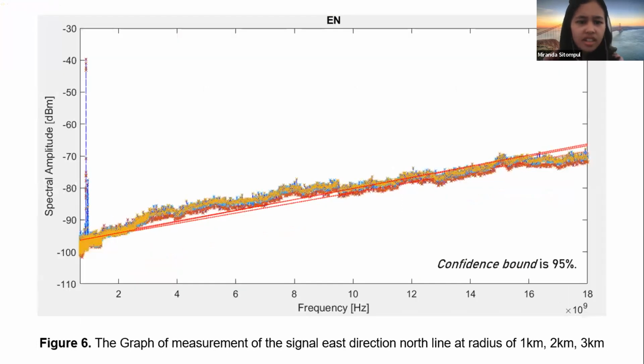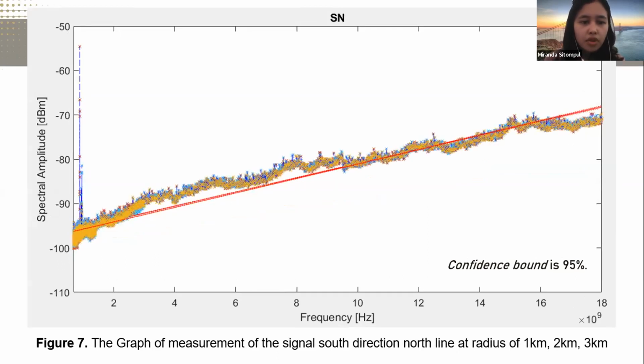This is the graph of measurement of the signal east direction north line at radius 1 until 3 kilometers, and we can see the spectral amplitude is in the range minus 40 decibel to minus 105 decibels. And we can see that the data obtained are similar. Okay, this is the measurement of the signal south direction and north line, and the spectral amplitude is in the range of minus 45 decibel to minus 100 decibel.